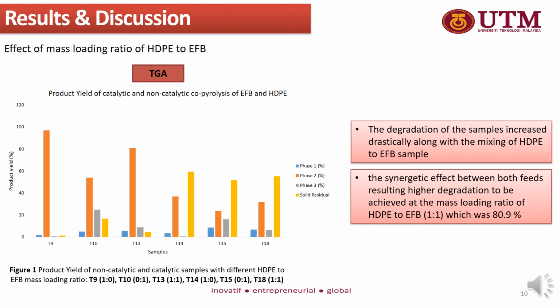Then come the results for thermogravimetric analysis of the catalytic and non-catalytic samples with different mass loading ratios. In this graph, there are four phases to be discussed. Phase 1 is where decarboxylation takes place. Phase 2, which is the main phase, indicates the thermal decomposition of organic compounds. The third phase is where aromatic structure degradation happens, and finally the last phase is the solid residue that remains, also known as the remaining char. According to this result, the degradation of samples increased drastically along with the mixing of HDPE and EFB. The synergetic effect between both feeds resulted in higher degradation being achieved at the mass loading ratio of HDPE to EFB of 1 to 1, which states 80.9%.